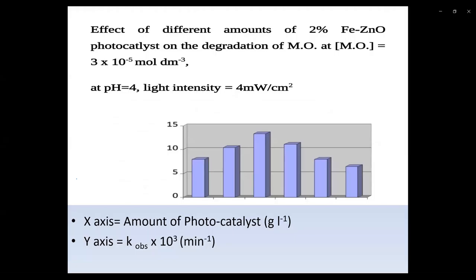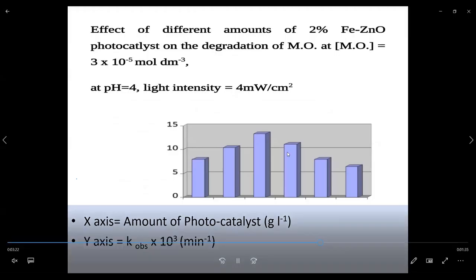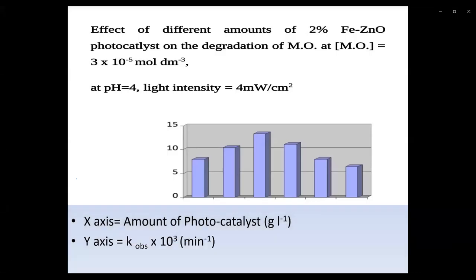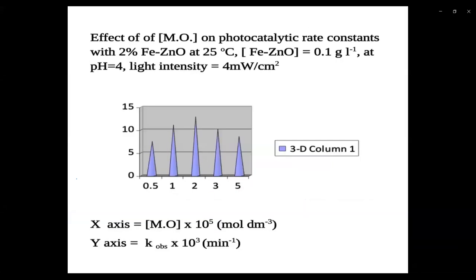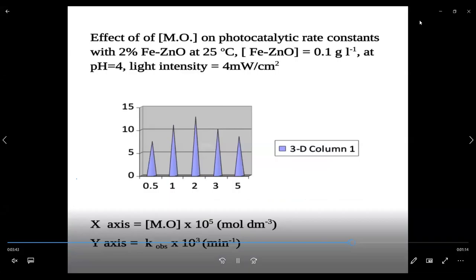As the amount of catalyst increases, the degradation process increases and reaches the maximum optimum range at 0.1 gram. After that, it goes on decreasing. It reaches the maximum, then upwards it decreases. So maximum activity it shows at 0.1 gram per liter. This graph shows the influence of the amount of methyl orange.